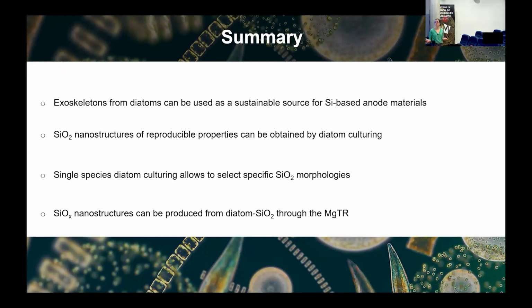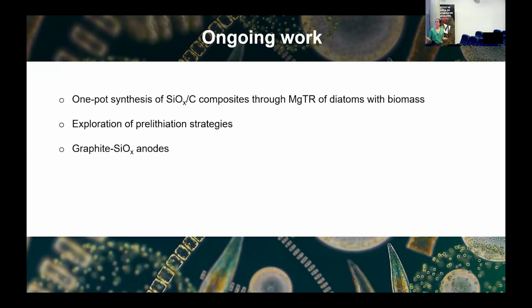We are working on producing SiOx from diatoms through magnesium thermic reduction. Some of the ongoing work is to try one-pot synthesis of SiOx carbon, using the biomass in diatoms and trying to do the magnesium thermic reduction and the annealing from the biomass to this carbon layer in just one pot. We will have to explore pre-lithiation because when you have these inactive phases, the silicates, you need to do some pre-lithiation. And now we are moving to graphite SiOx.